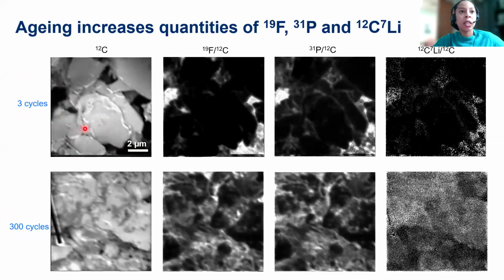We see 12C all over, of course, but when we compare 19F12C, for example, we see there's almost no 19F over the sample surface and a significantly higher signal in the more aged sample. And we see similarly for 31 phosphorus, and very much the same type of increase in signal for 12C7Li. So as you age the cell, we see that these SEI components in the layers grow within the sample.